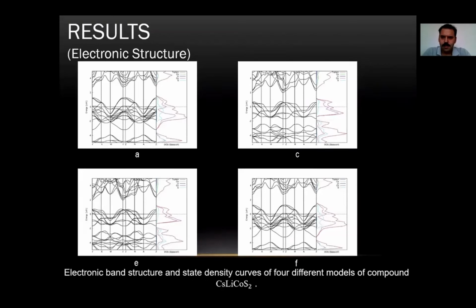Here I would like to talk about the results we obtained regarding this electronic structure. Electronic band structure and state density curves of 4 different models of the title compounds are given above. In the above graphs, the electronic band structure was drawn along the high symmetry points in the first Brillouin region. The Fermi energy level was taken as 0. As can be seen from the graphics, all models of the title compound show metallic character.